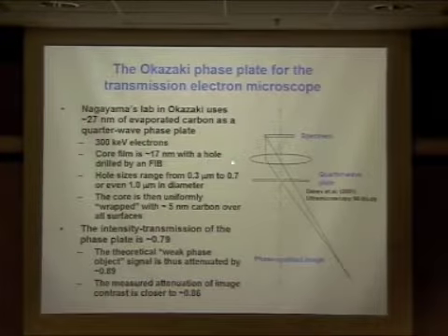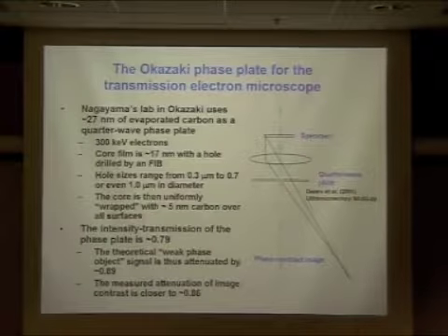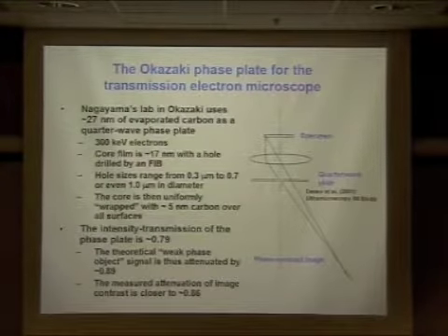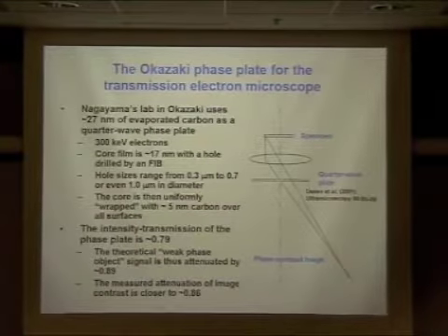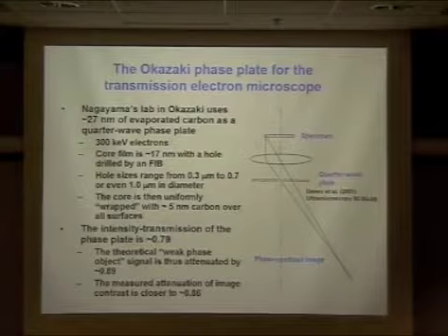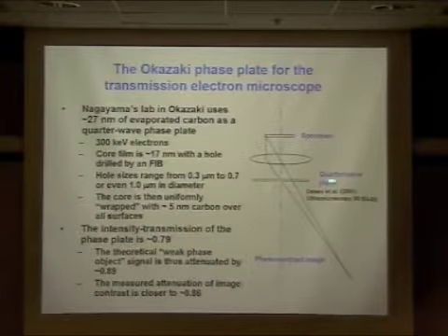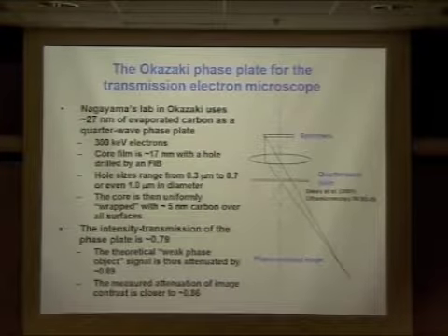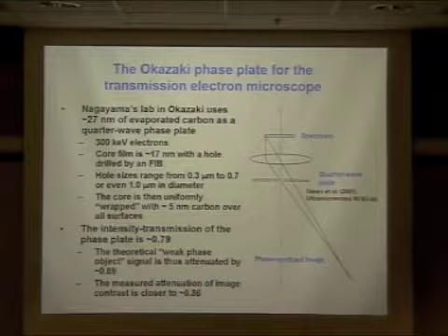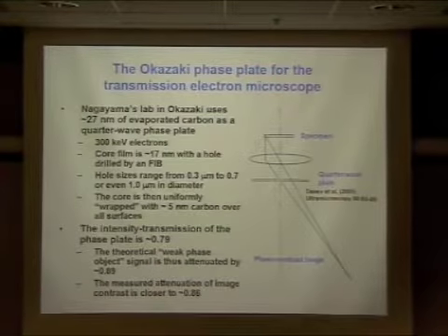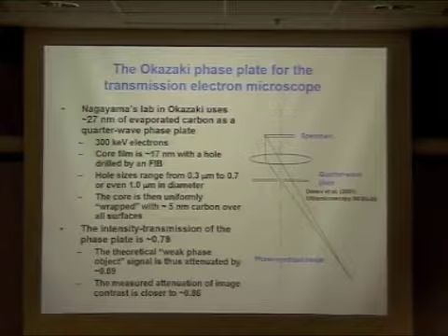The real reason is that too many of the electrons that have to go through the phase plate and get a phase shift due to the inner, or constant, component of the Coulomb potential are scattered by the AC components of the Coulomb potential of the carbon film. You lose too many electrons. Well, I didn't change that opinion until I started to see real, genuine, beautiful results coming out of the laboratory a couple of years ago.